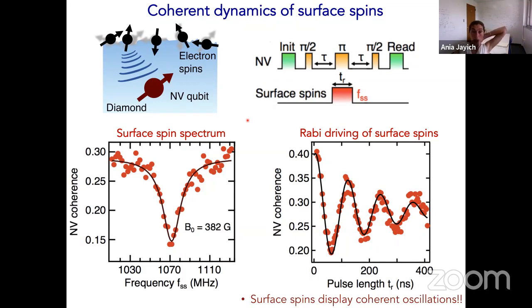So it turns out that we've identified that surface spins, and there's been a few people working on this, are indeed one of the sources of decoherence at the surface, the presence of these paramagnetic spins. Interestingly, though, we are able to detect the dynamics of these surface spins, and we see that their surface spin spectrum is actually quite narrow. So in fact, these surface spins have reasonable coherence times. In fact, we can even drive Rabi oscillations of these surface spins.